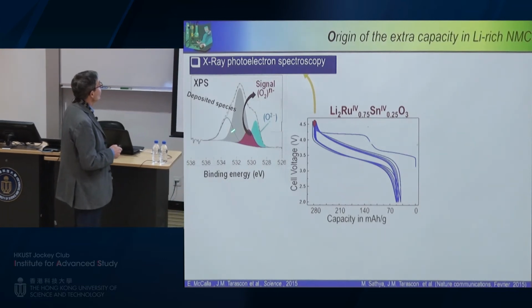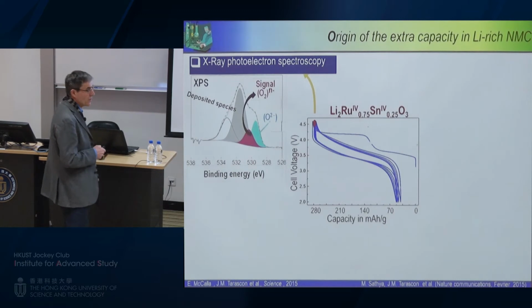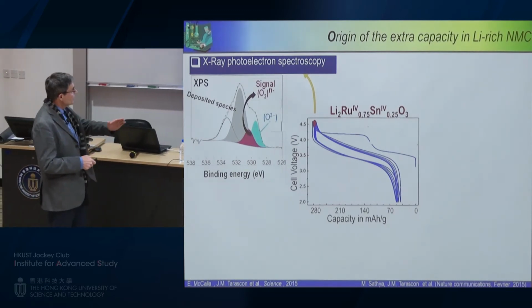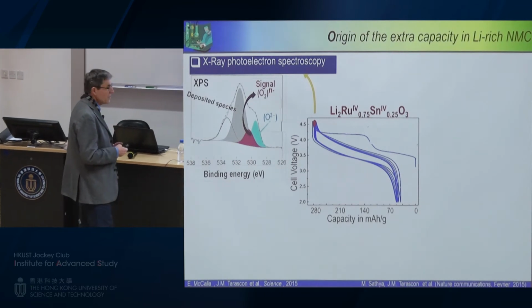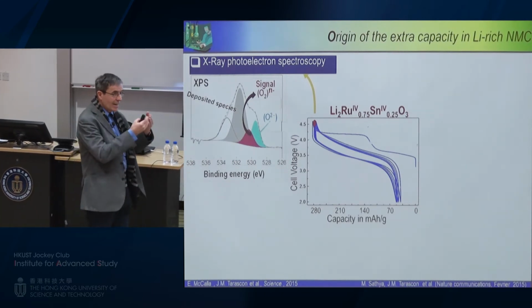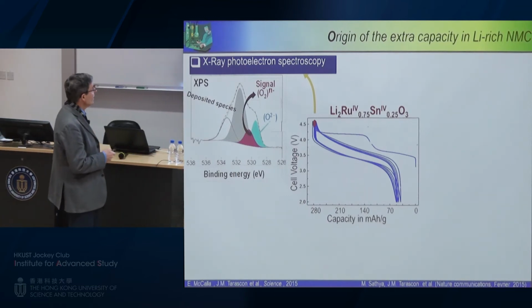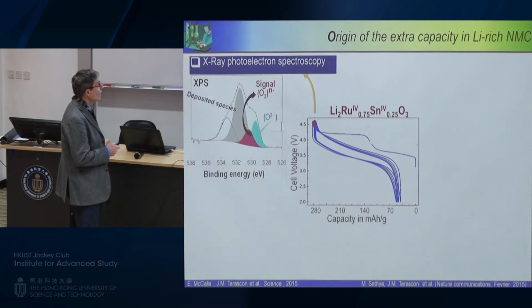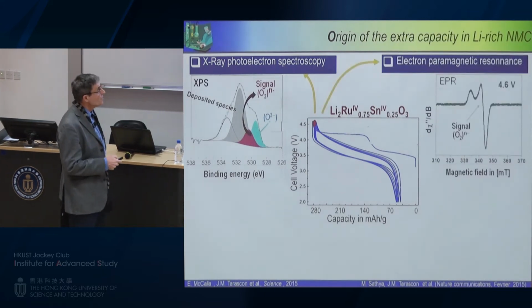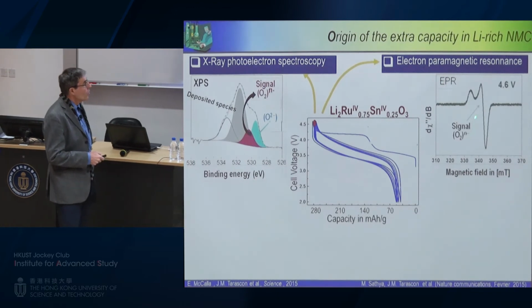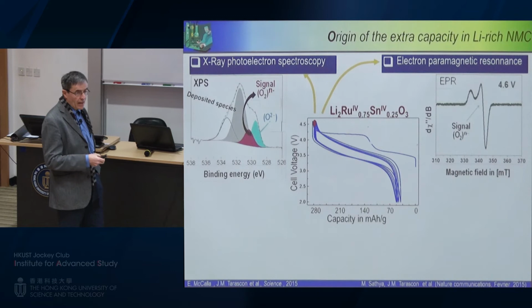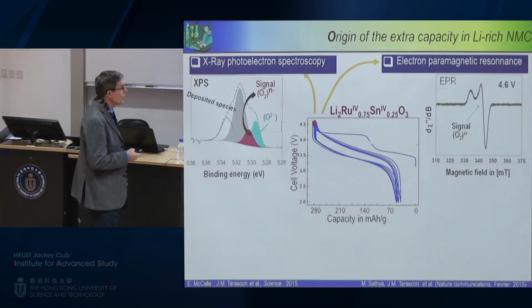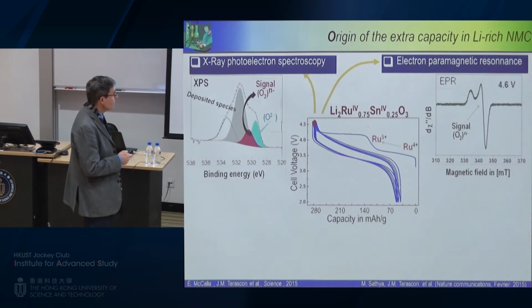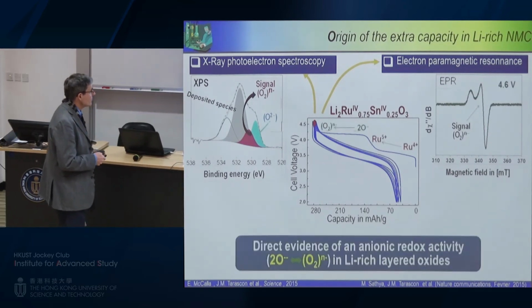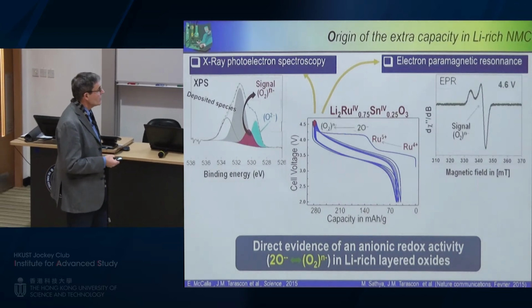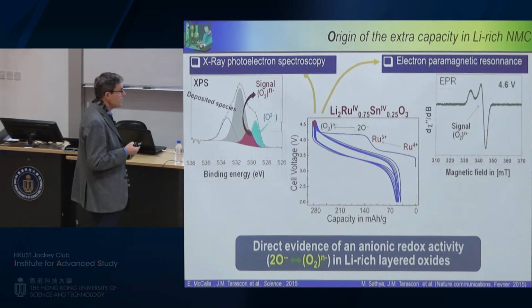And then, beside all the deposit species, you have the appearance of this reddish peak, which you can see here. Its binding energy is shifted toward higher value, which means that the oxygen is less electronegative. So in this case, we have peroxo-like species. And to confirm this, we have done electron paramagnetic resonance, where we could observe very nicely the signal associated with this peroxo-like species. So this was really the first evidence of the presence of anionic redox activity in this lithium-rich layered oxide.